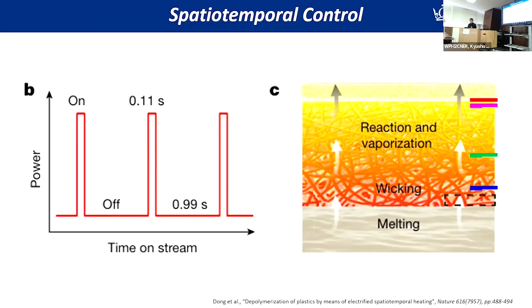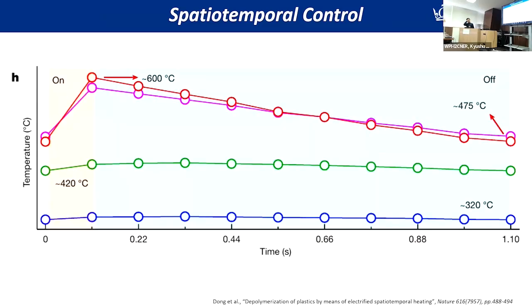I will quickly go through the final 3 slides, and that is from the electrification work in a Nature paper. It indicates using pulses to control rapid heating, and they were creating a temperature gradient between different spots. You will see this line here. They were actually creating different time and temperature gradients in the system. In this case, they could then improve the selectivity and the yield of the targeted products and prevent the following side reactions.